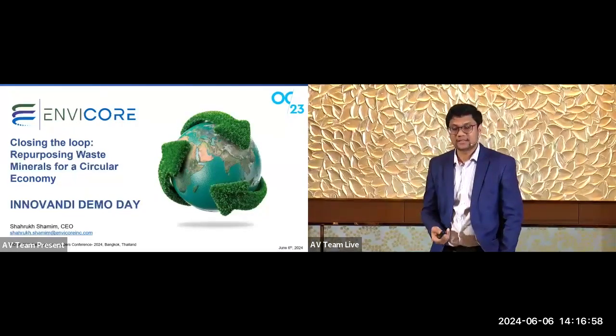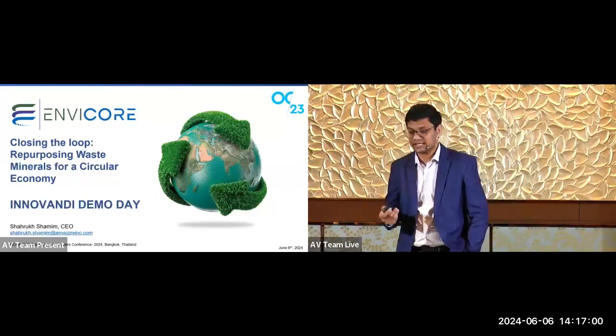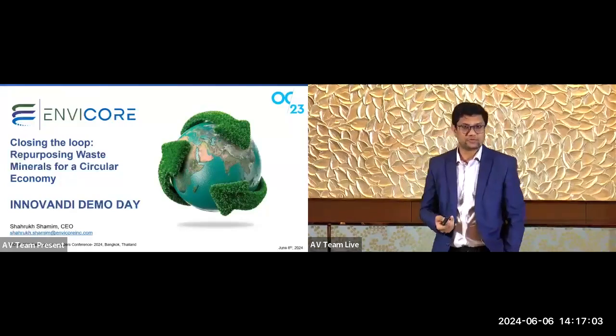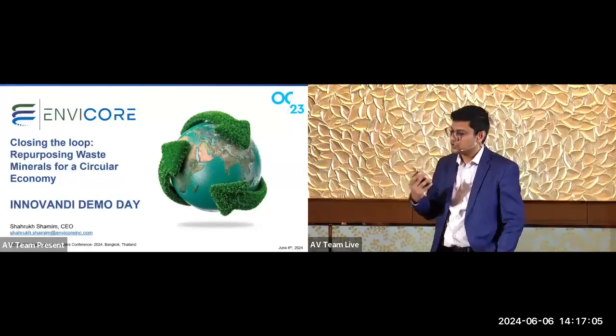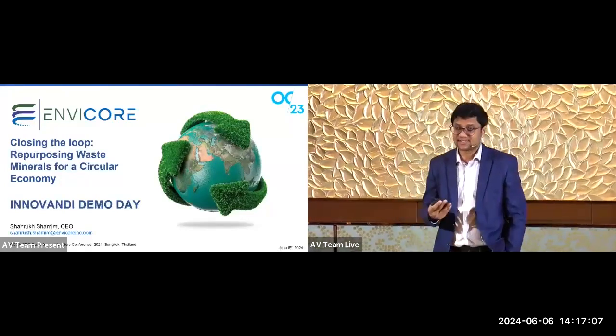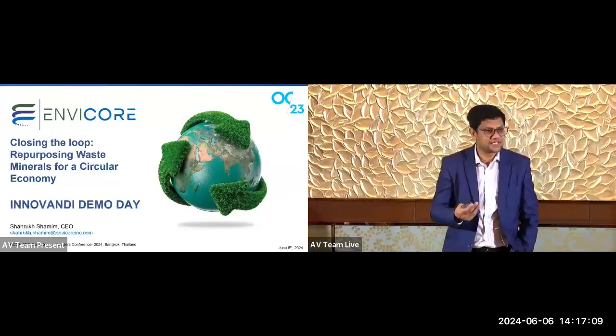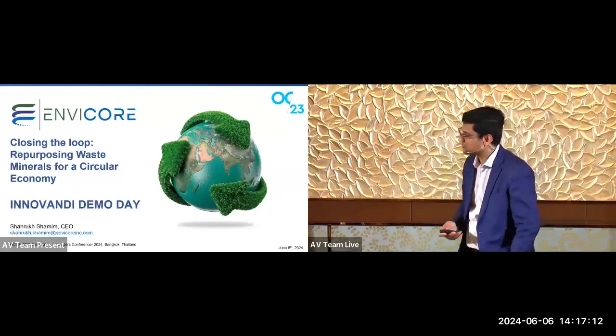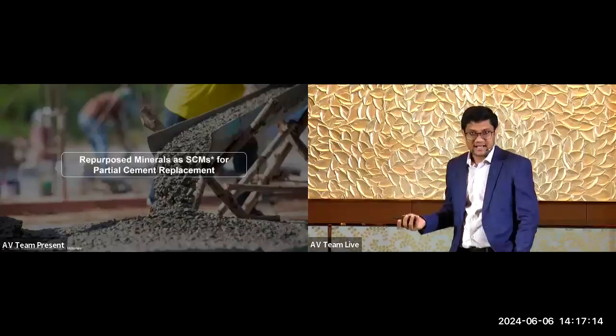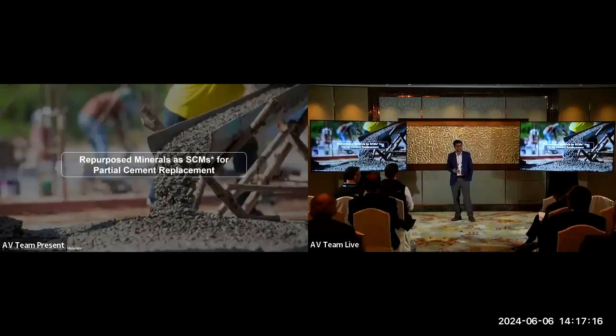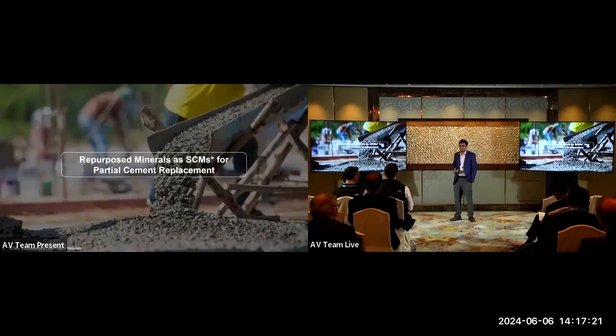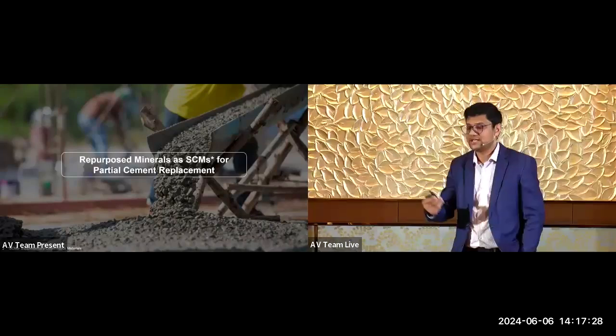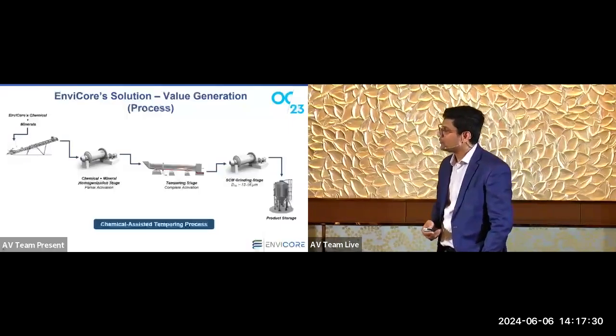We are supporting the construction, or more specifically, cement and concrete producers in pushing the decarbonization limit, specifically by transforming different types of mineral feedstocks into SCMs. And our idea is to go as high as possible in replacement. We're starting with 20% cement replacement in the mortar mix, and assessing the performance of the material before and after treatment with our technology. Now, how do we do it?